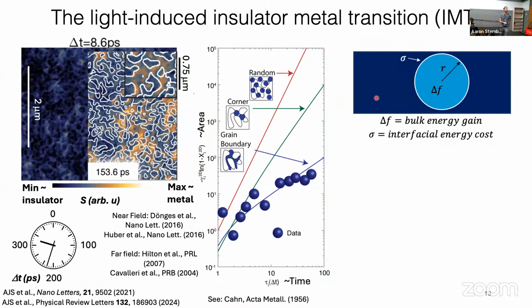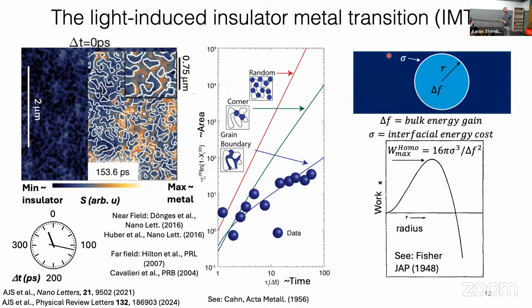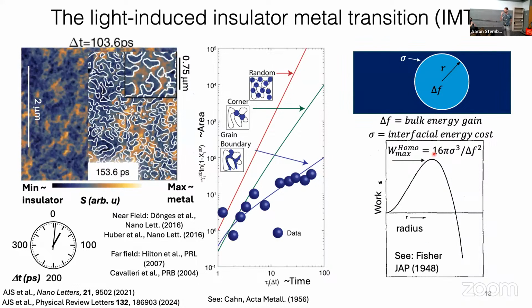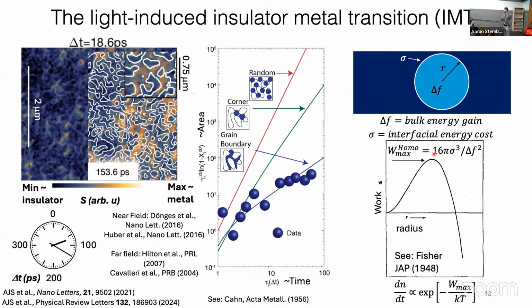In classical nucleation theory, you basically assume a spherical cow and approximate this domain as just being a sphere with a given radius. And then that competition between bulk energy gain and interfacial energy cost leads to a work barrier, where the system has to put in a certain amount of work to actually move into the new phase. And that delays nucleation. So there is a nucleation rate that depends on the height of this work barrier.